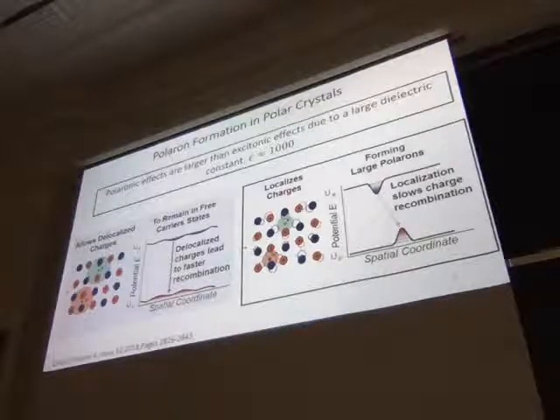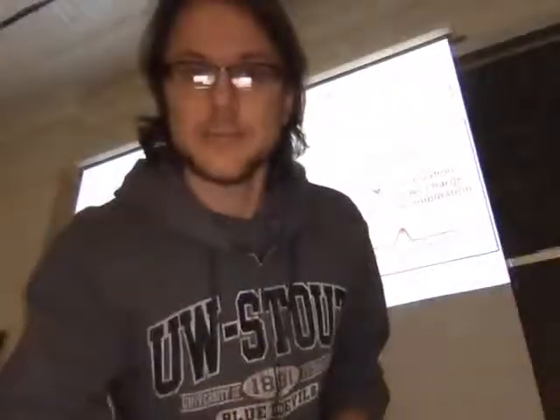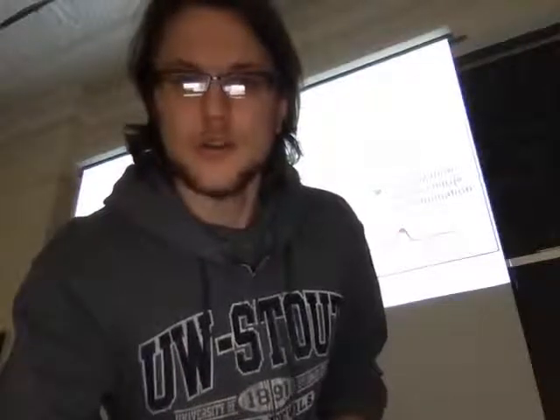But compared to that, if you have polaron formation, you see that the electron and hole become a lot more confined. If you have your electron here, it's going to be pulling positive nuclei towards it and repelling negatively charged nuclei away, and vice versa for the hole. So essentially what that does in your spatial coordinate is it localizes your charges into two distinct regimes. Notice that you consider these as bound states, and they have these lines that represent electronic states for the bound polaron. This is just introducing the idea of polarons in these perovskites.